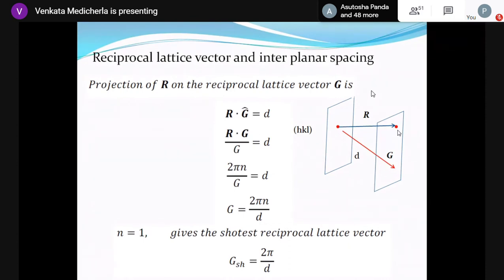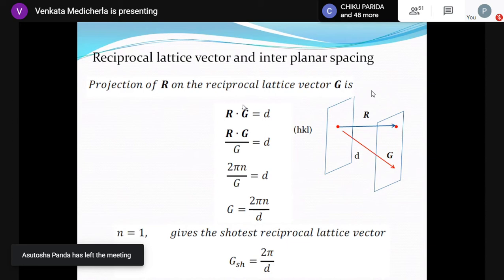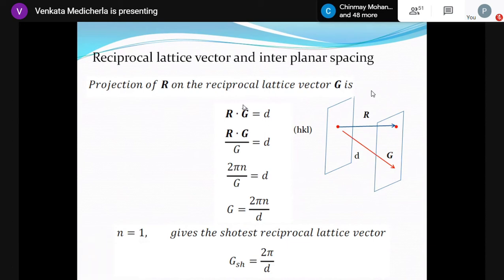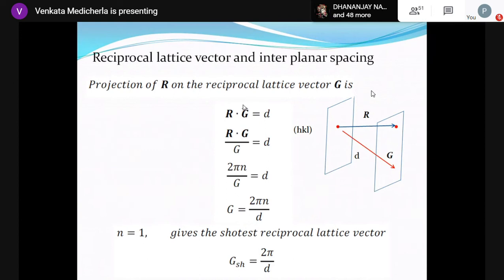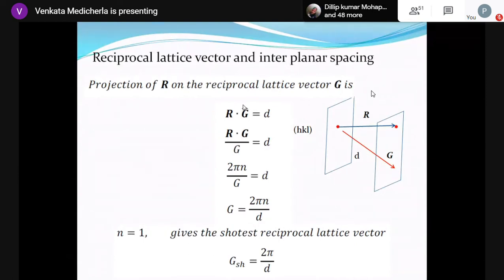r is not perpendicular to the planes — it is at some angle. The projection of r along g is r dot g-hat, the unit vector along g. That gives d, the distance between the planes. This can be written as r dot g divided by the magnitude of g. So r dot g by |g| equals d. Now r dot g is 2πn from our definition of the reciprocal lattice.